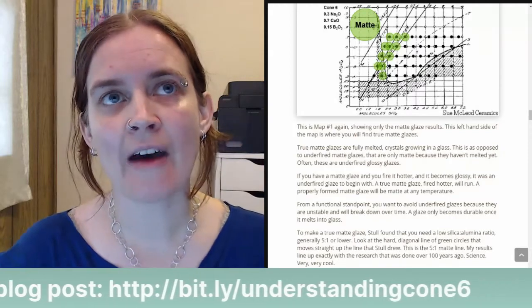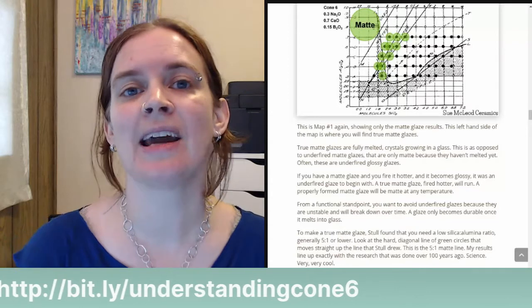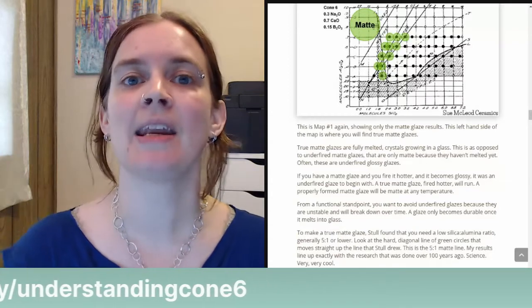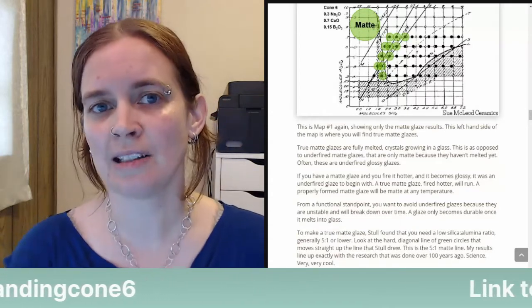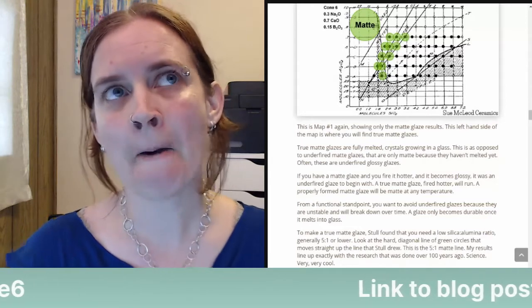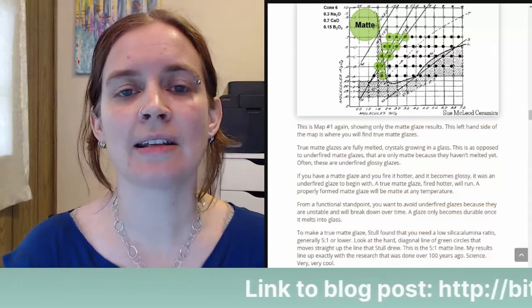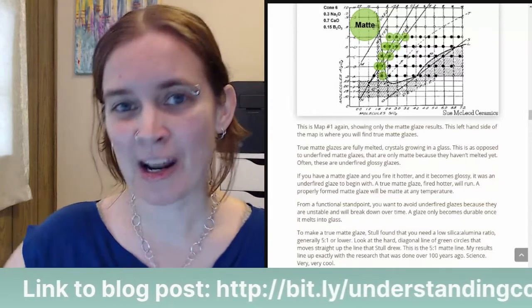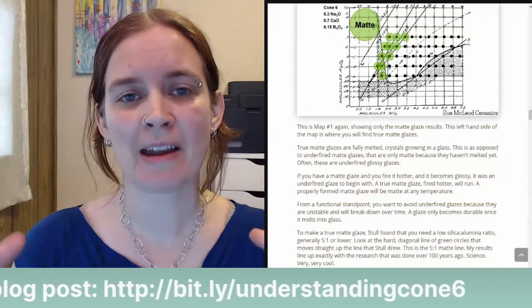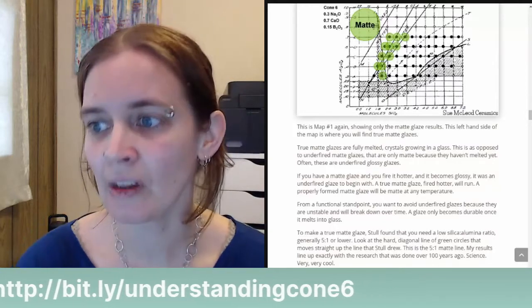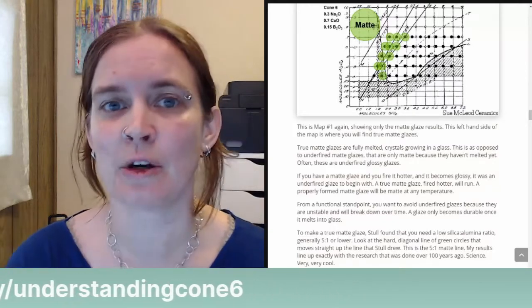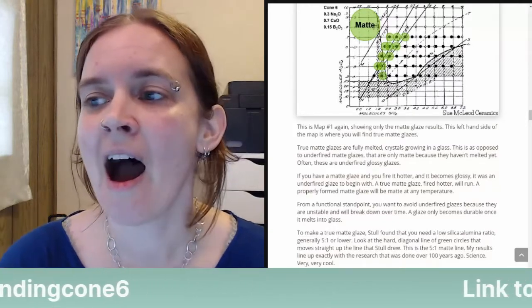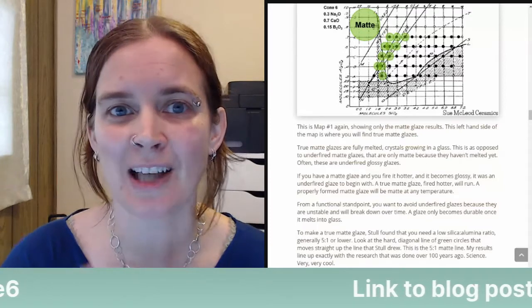But if you have a glaze that is matte because it has a lot of titanium in it, then your cooling cycle is going to make a difference. I have this glaze that has 4% titanium dioxide. When I fire it at home in my really small kiln, that cools really fast, in like 8 hours, then that glaze comes out glossy.